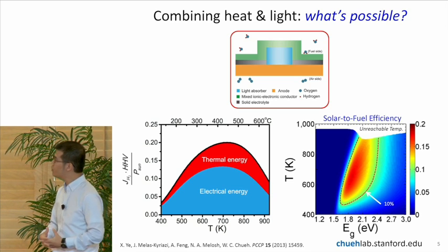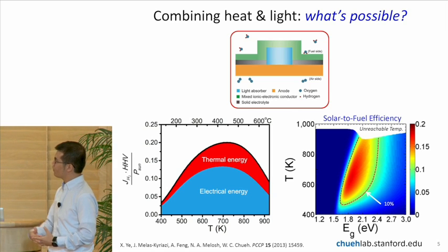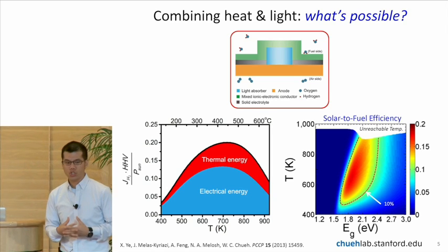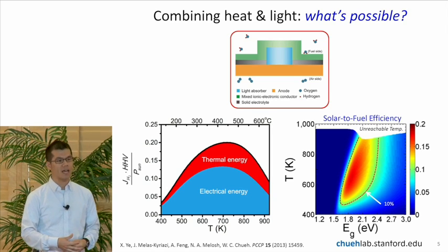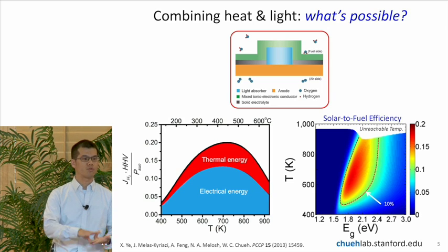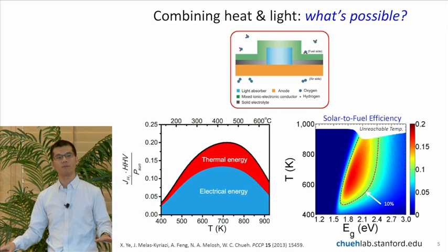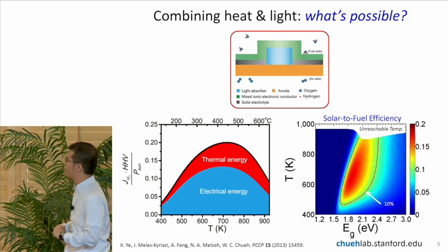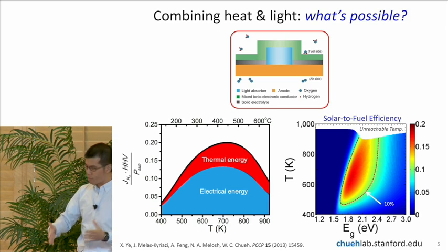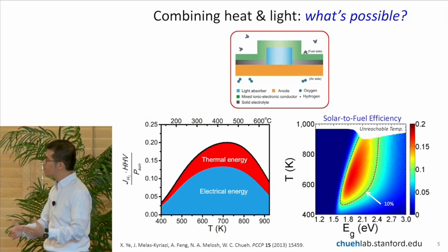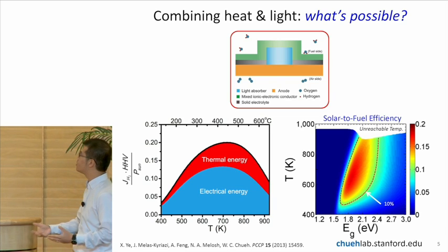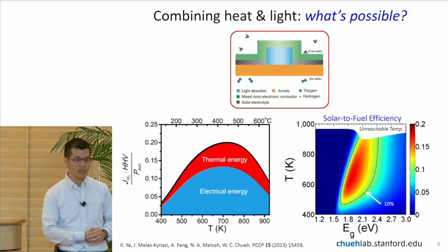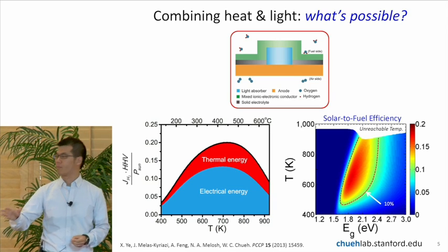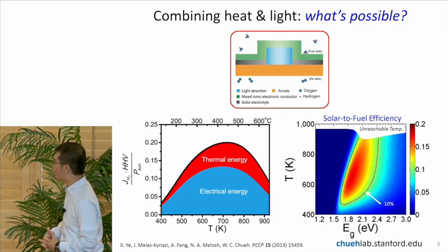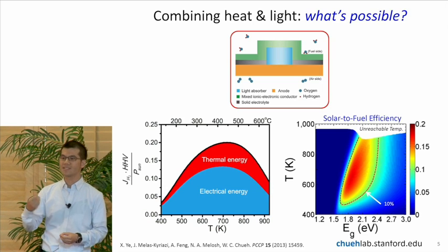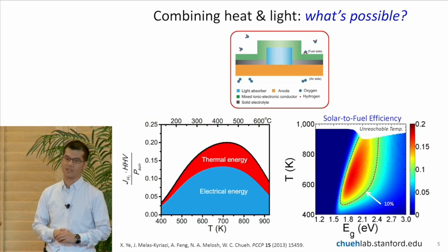The materials for this do not exist today, but we made a simulation nevertheless. And what we found was really quite surprising. If you look at the plot on the left, that shows the amount of energy that comes from the light and that comes from heat as a function of temperature of the solar fuel generator. So as you go from room temperature, you use mostly what we call the electrical energy, so that's the energy that comes from the generation of electron hole pairs. But as you go up in temperature, say for example at 400 or 500 degrees Celsius, then you get a significant thermal contribution to the efficiency.